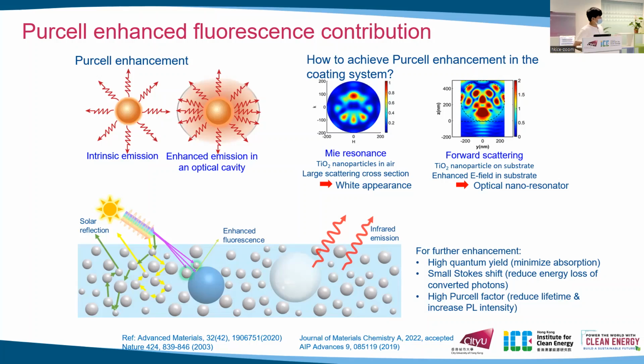But to further enhance the Purcell effect, there are some points that should be addressed. First, high quantum yield is needed, because a phosphor with low quantum yield will increase the energy loss, and a small Stokes shift is required to reduce the energy loss of the converted photons. And finally, we want to achieve a higher Purcell factor to further reduce the lifetime and increase the PL intensity.